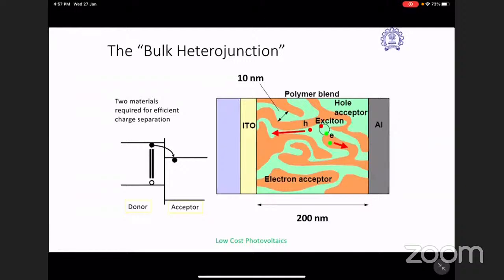So you have the important advantages of the organic and inorganic both together in the single device. Or I can have the inorganic device and organic device separately, but they both are sandwiched together. I make a tandem solar cell. So I can make use of the electronic band gap of the inorganic and the electronic band gap of the organic as well, and I can stack them on each other. And then I can make a device which will be using the efficiency of both the devices, and then I will be having much higher efficiency.